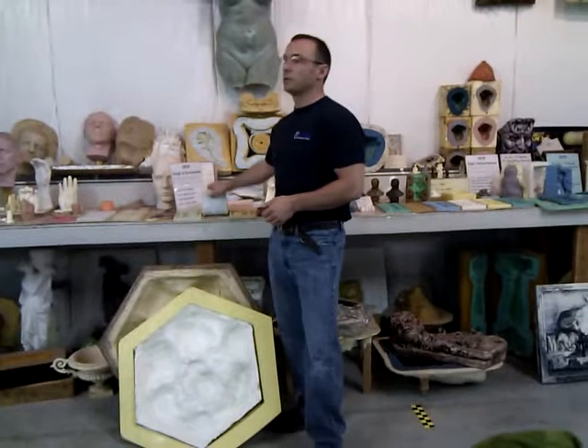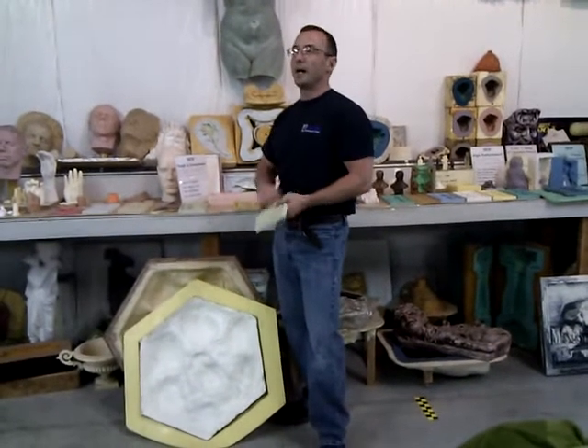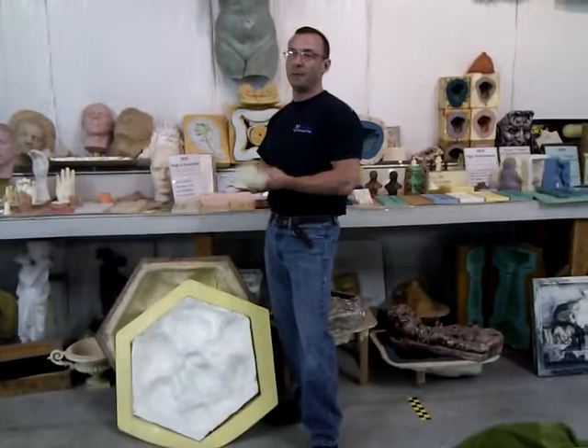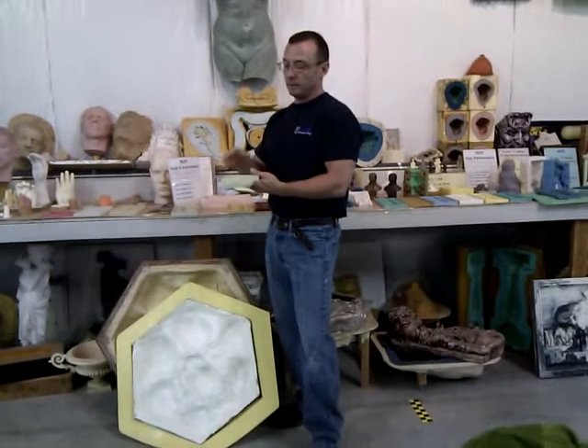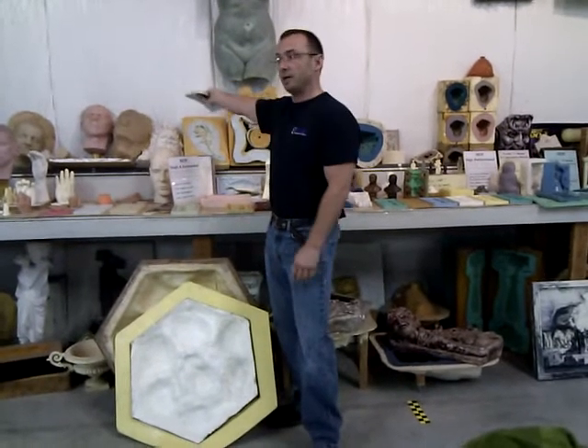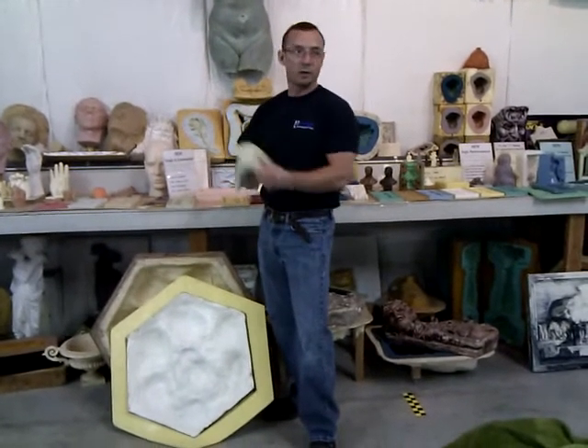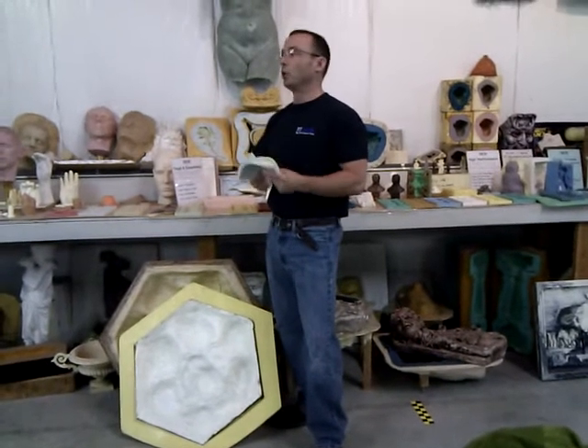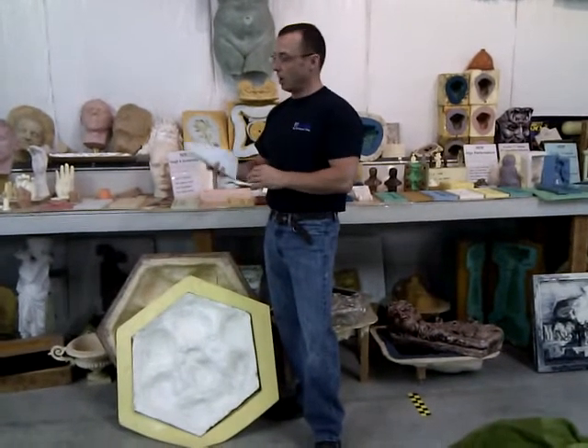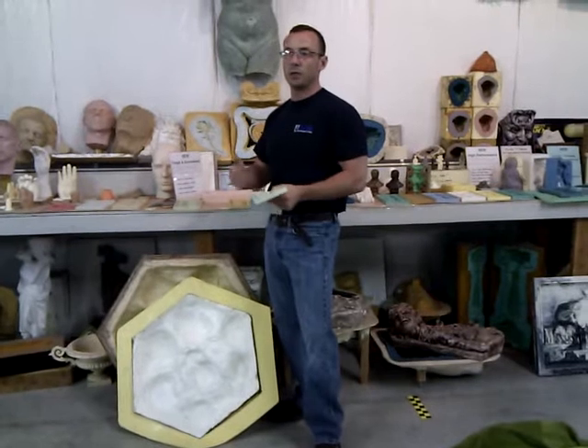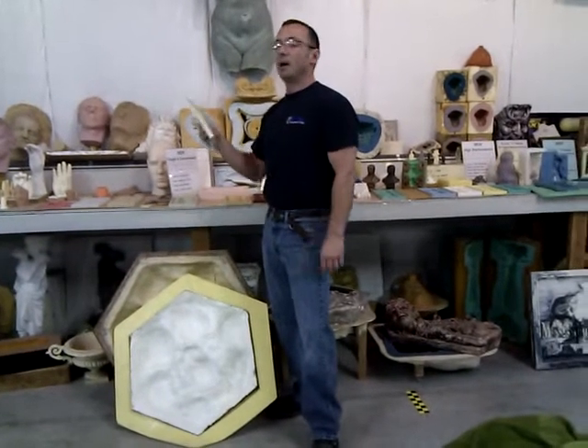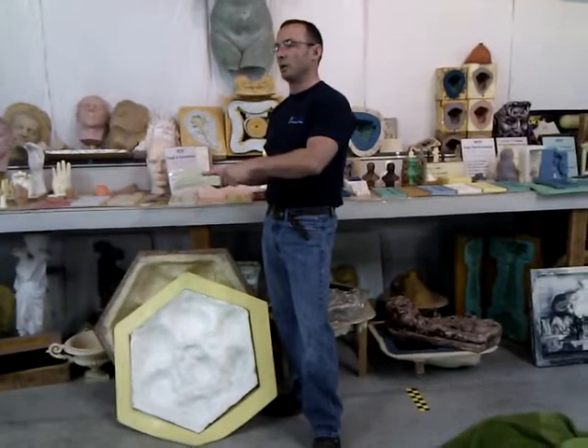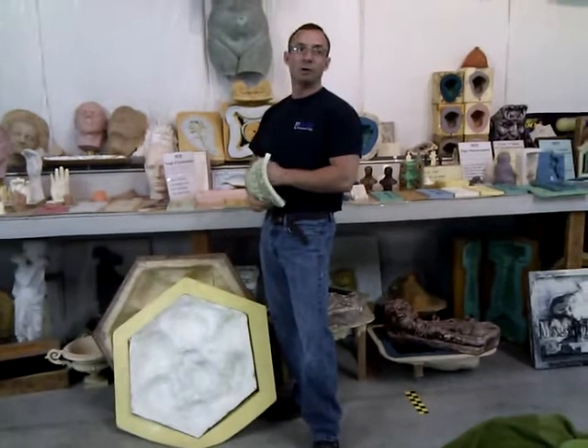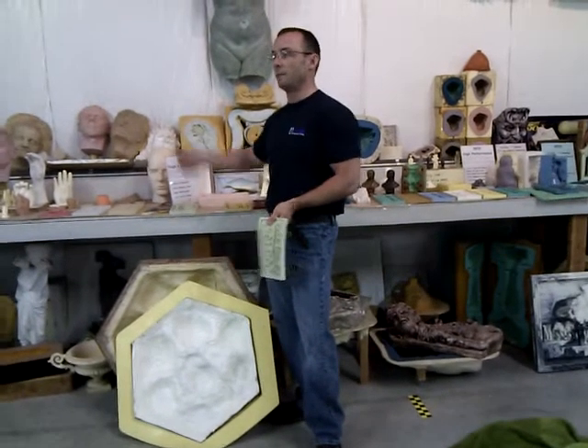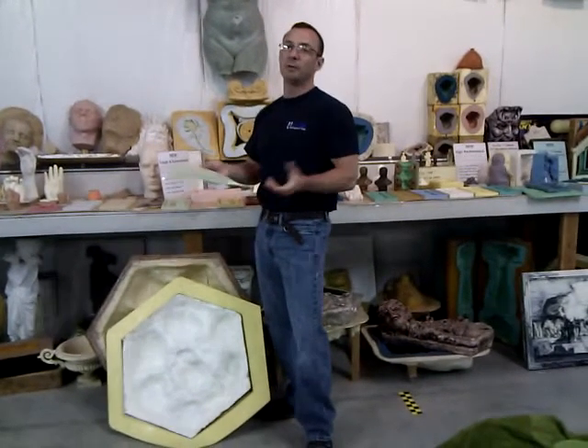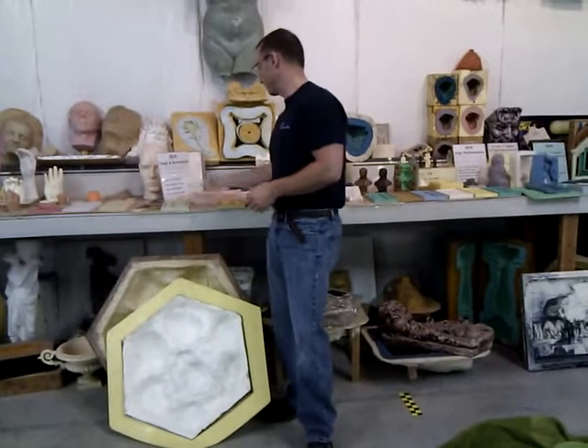The tin silicones do not have long library life. So if I make a mold and put it on the shelf for 10 years, I come back to it and I flex it, it's just going to break apart and it will be no good. So tin silicones are best if you're using them in a situation where I'm going to take 100 castings this month or this year, so the mold is going to wear out from use long before it wears out from time. Your typical library life might be 2 to 5 years depending on your storage conditions.